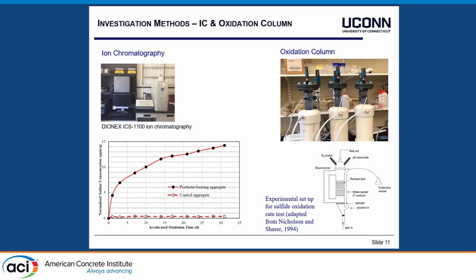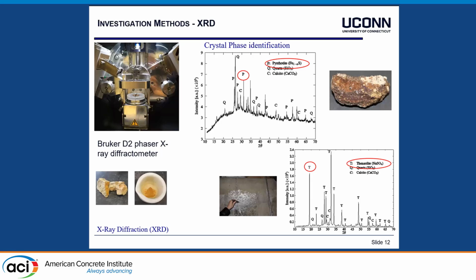The oxidation column, which is currently set up at UCONN, uses a system where the material is packed here in a column, and then there is water flowing through the column. There's oxygen being supplied through here, so there is a circulation going on. And then you have the presence of water and oxygen with the pyrrhotite material. It could be containing pyrrhotite, could be pure pyrrhotite, could be synthesized pyrrhotite, whatever you want to investigate. And then you can measure the iron and sulfate release, and based on this, you can quantify the reaction rate.